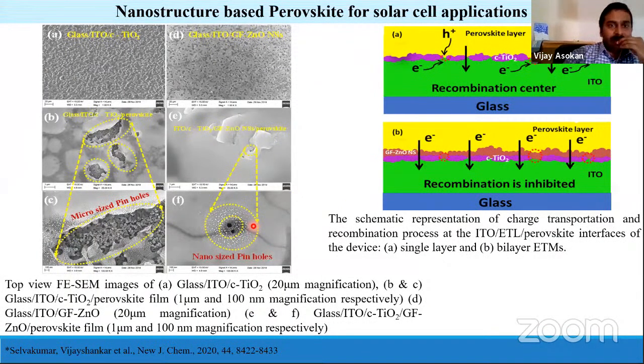Then the more important thing about such zinc oxide nanostructures in the titanium dioxide electron transport layer is that the micro-sized pinholes are now reduced to nano-sized pinholes. That's why it is important to combine titanium dioxide and zinc oxide, because it helps avoid recombination. When we have micro-sized pinholes, there is a possibility for electron and hole interactions as shown here. But when we have the green synthesized zinc oxide nanostructures combined with this compact titanium dioxide, such recombination can be inhibited. That's important to understand about micro-sized pinholes and nano-sized pinholes within the electron transport materials.